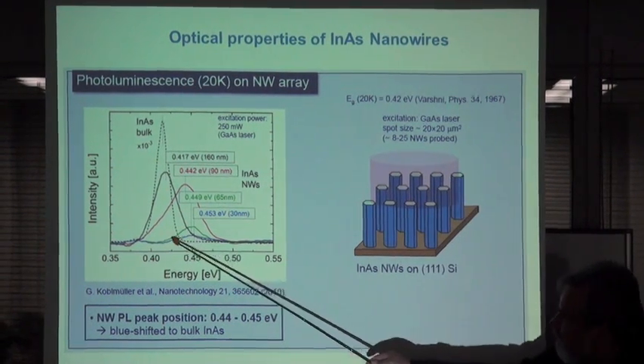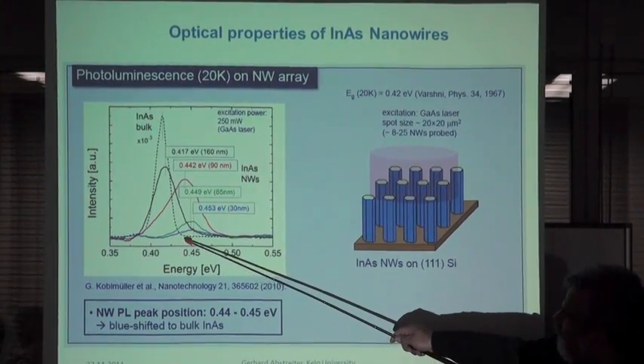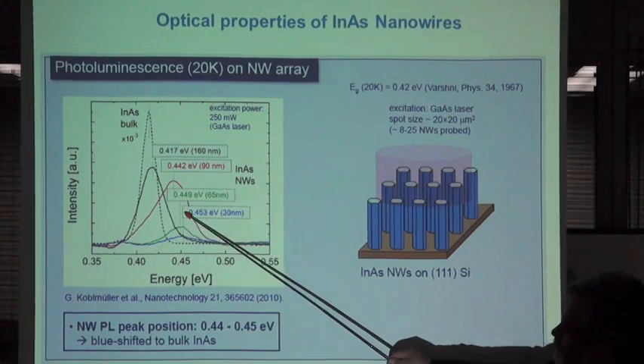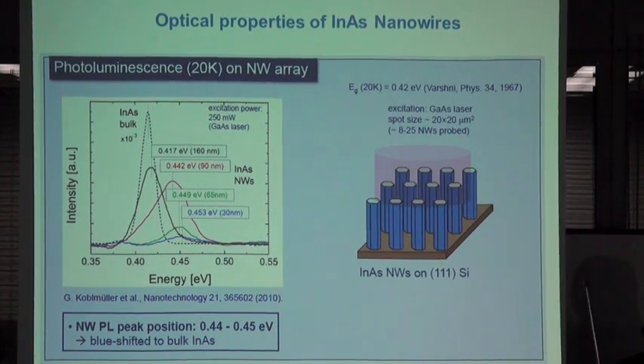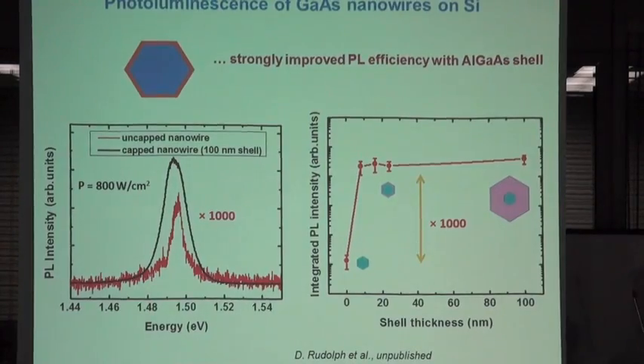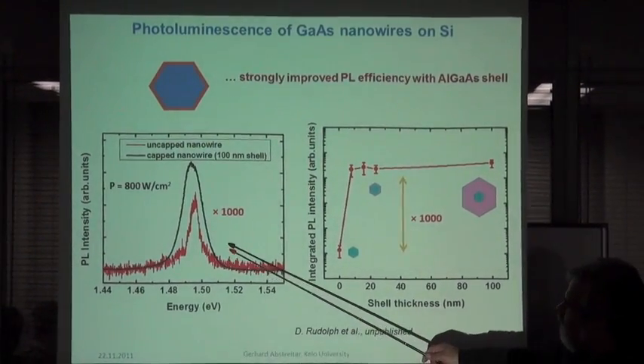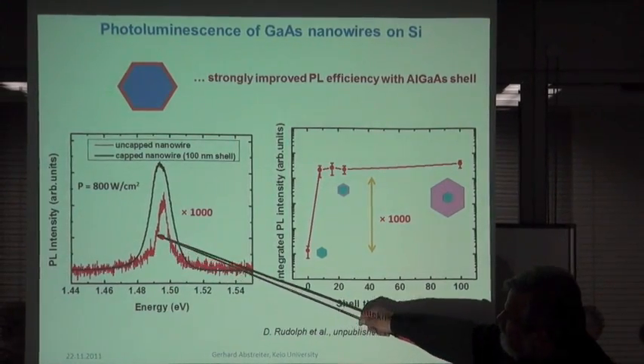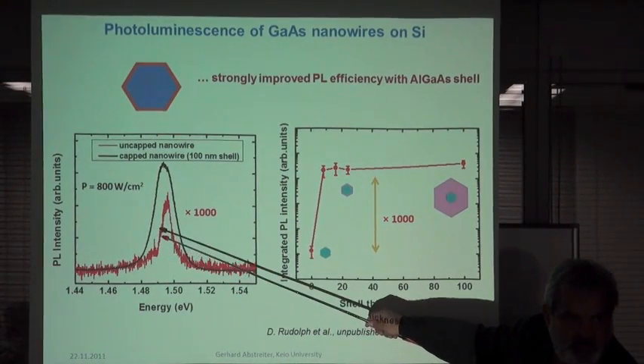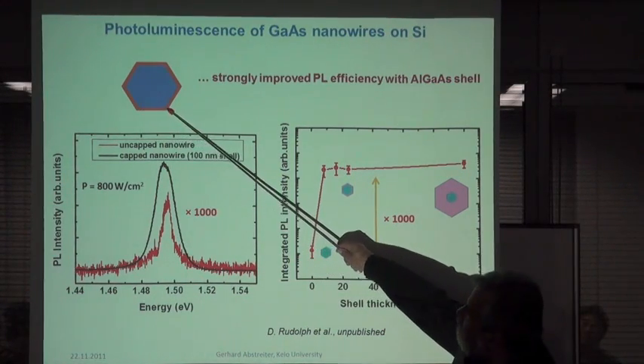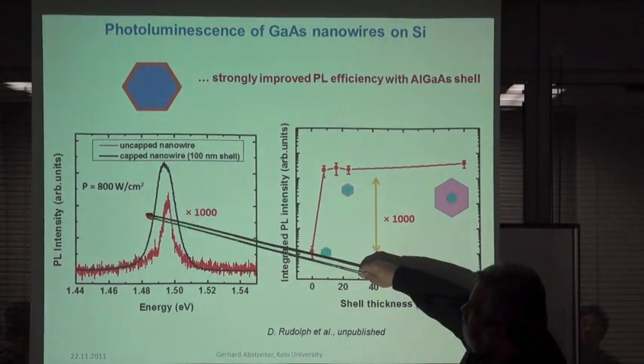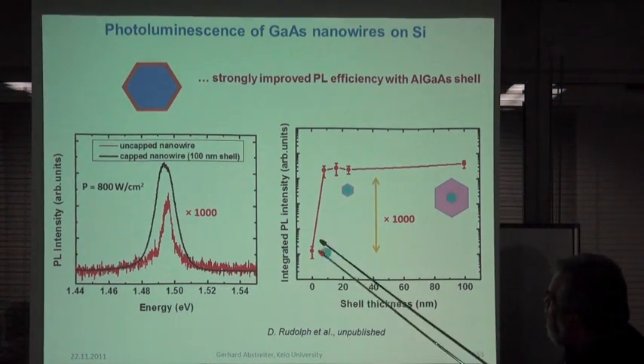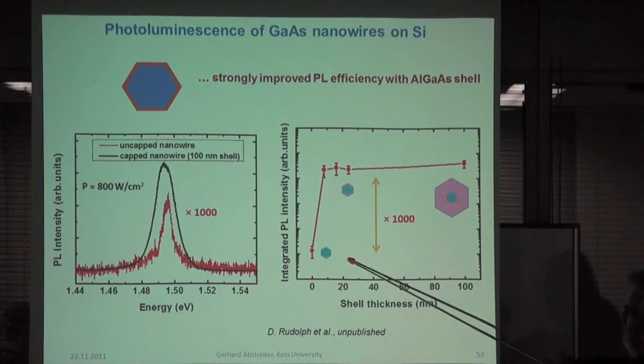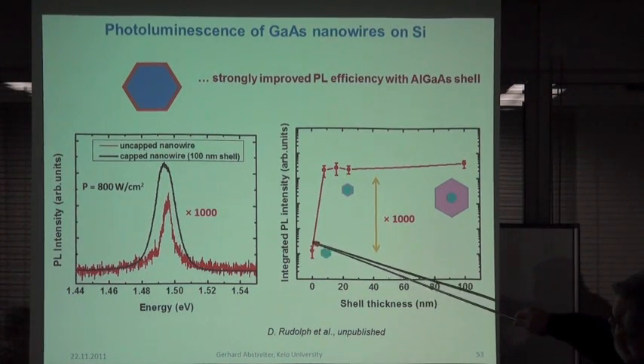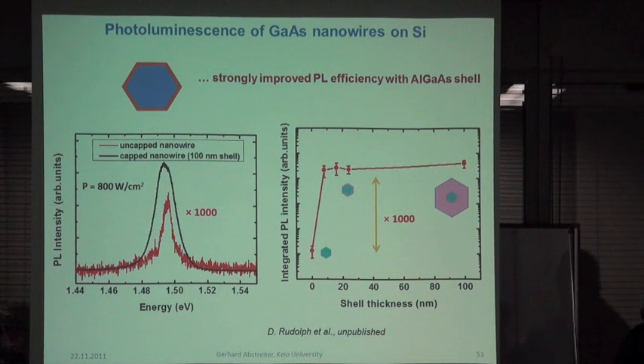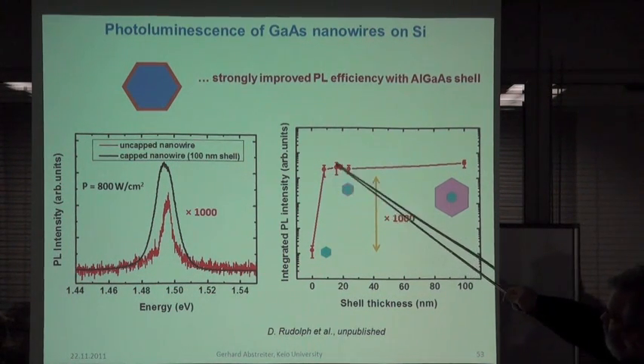This is in the mid-infrared. It's at 0.4 electron volts. They all show luminescence. We get the blue shift, which we believe, however, is due to the structure of these indium arsenide nanowires. And in gallium arsenide, you see this is a relatively thin nanowire. This doesn't show a lot of luminescence at the gallium arsenide gap, basically. But if we cap it a little with aluminium gallium arsenide, protect the surface, we get the immediate effect of 1,000 times more intensity. And a very thin cap is already sufficient. So this is bare gallium arsenide, and this is actually averaged over 15 different wires from the same growth. So this error bar is the statistical variation in the intensity.